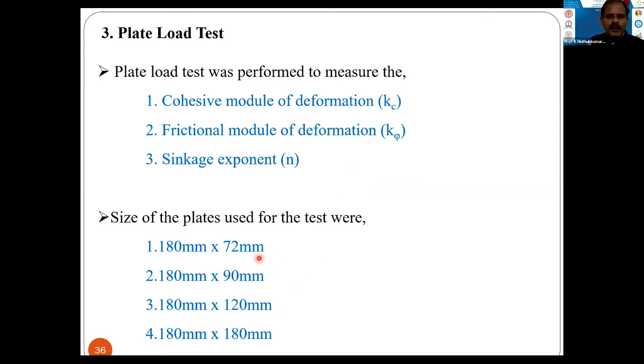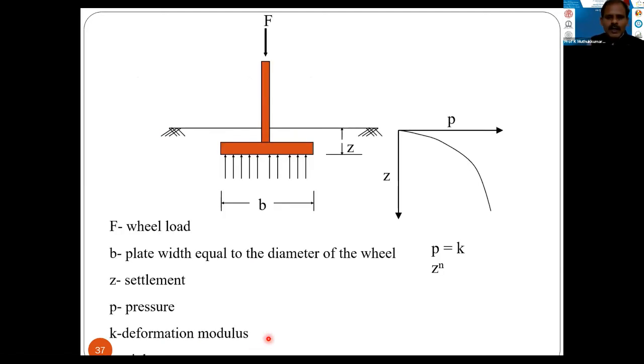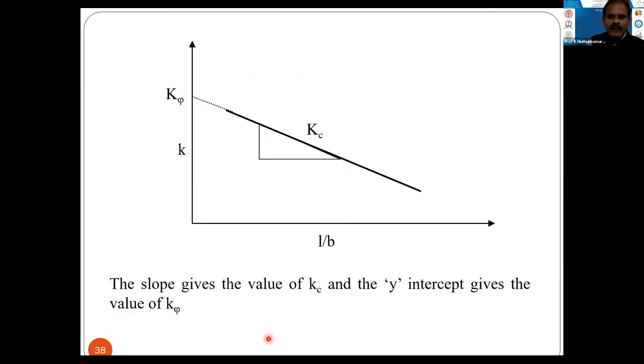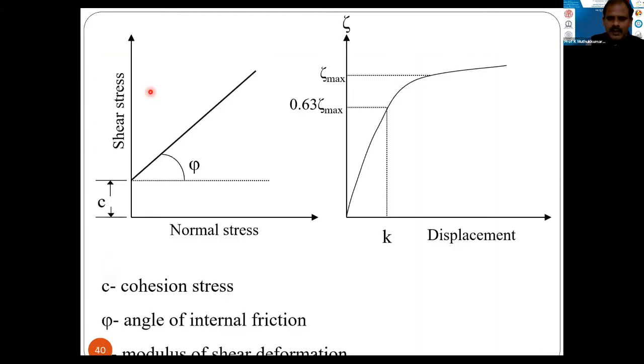For that, we have taken different aspect ratios of the plate, keeping the length as a constant 180 millimeter, varying the width from 72 to 180, such that we maintain from 1 to 2 aspect ratio. That aspect ratio is basically what decides the slip as well as the friction of the wheel. Based on that, we have evaluated both the cohesive modulus and the friction modulus. And this is the developed material.